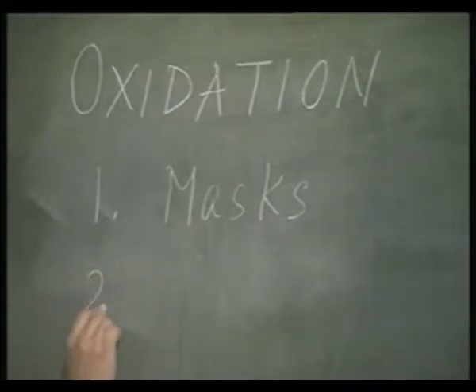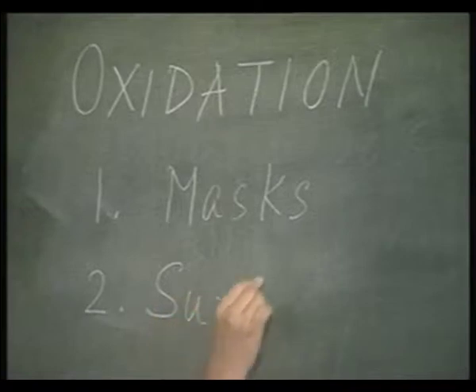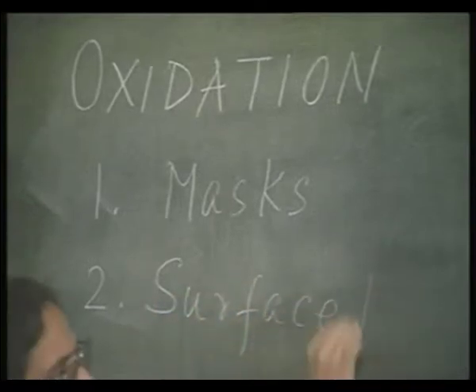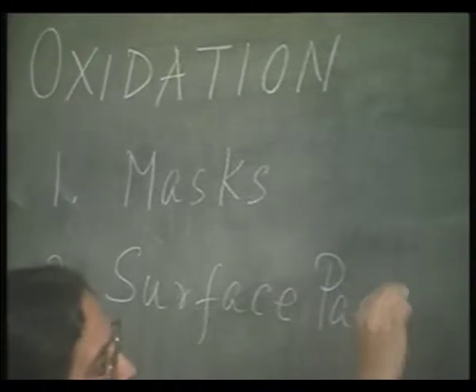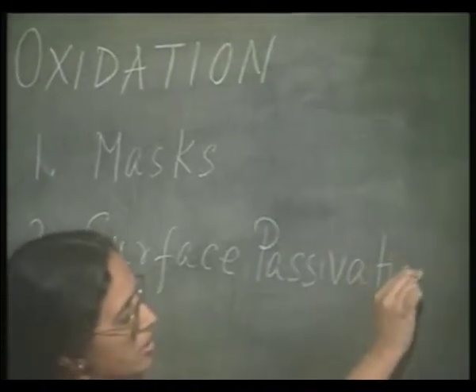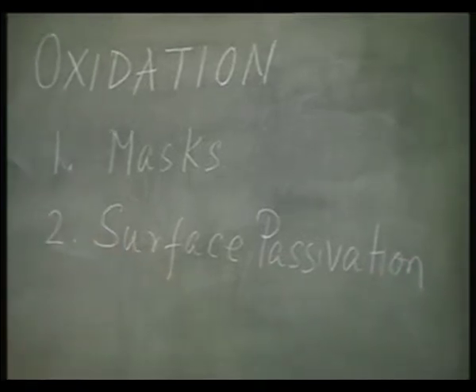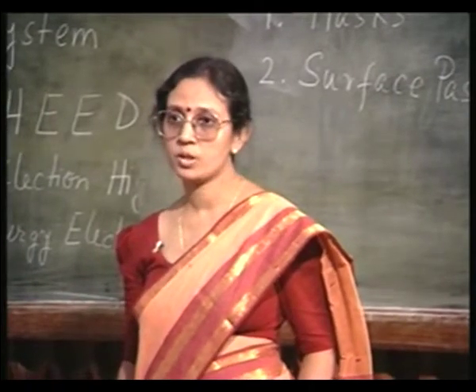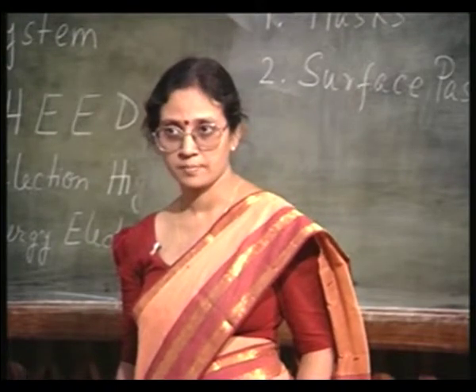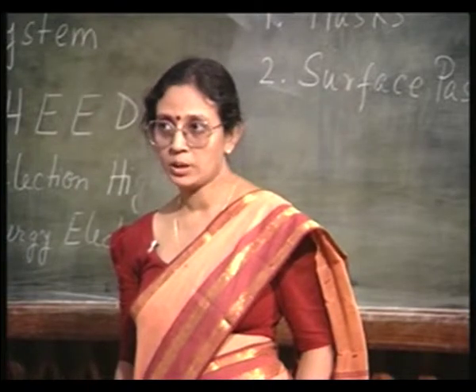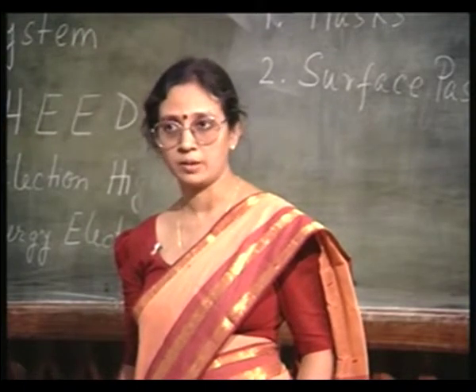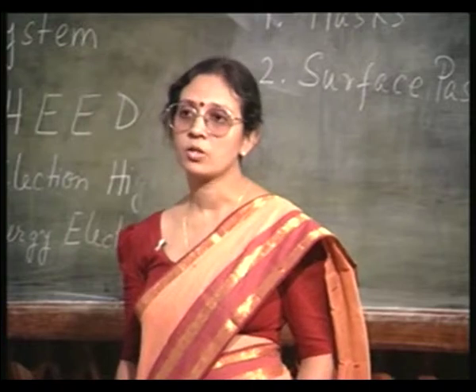This is also used for surface passivation. That is, after your device is fabricated, you do not want all the junctions to be exposed to the ambient condition. So, what is done usually is that any exposed junction is passivated by silicon dioxide. Only those portions are exposed through which you are going to take your metal contacts. Those portions are covered with metal. The rest of the surface is covered with silicon dioxide, and that acts as surface passivation.